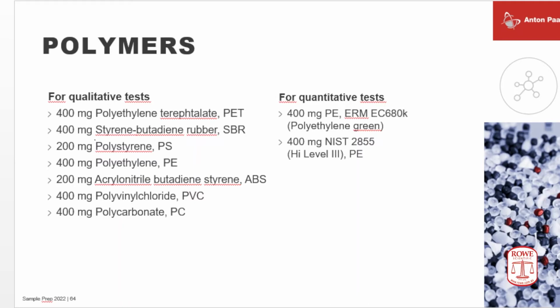What is extremely useful when digesting polymers, the instrument can be equipped with an optional magnetic stirrer. And magnetic stirring helps to mix samples and reagents. The difficulty with lightweight polymers is that they float on the surface of the acid, and when you heat up, maybe these floating polymer pellets would melt and form a solid layer on top of the acid, and this is unwanted because you do not have any exchange of material with the acid. When stirring such reactions, you keep the sample pellets distributed, and they offer a large surface to the acid and can be oxidized and decomposed very well.